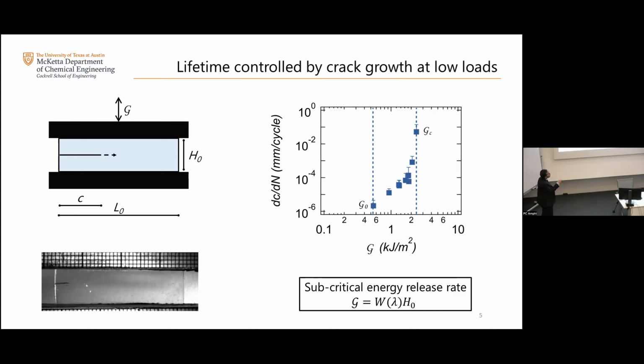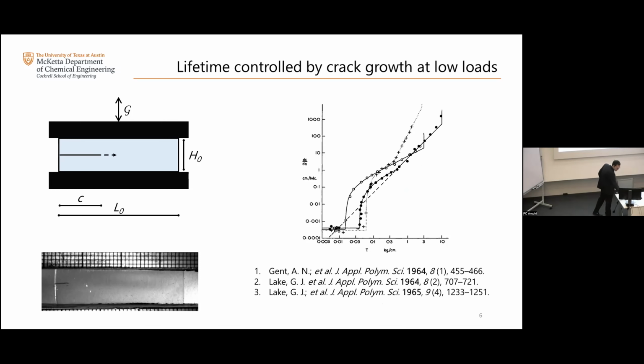At the other end, you have your GC, which is effectively the regime of the toughness, at which you open the crack so much that the crack catastrophically fails, and that's what I considered in the first slide. And then in between, you have a power law that people call Paris law, at which you have an increase in the crack growth rate with the applied G. Okay, so that's what you would measure, and that's the macroscopic behavior that you would probe in the system.